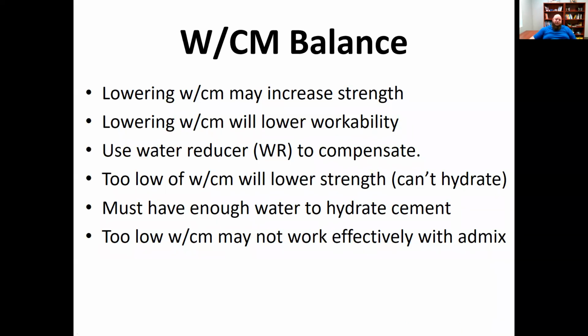The water cement ratio balance is all about lowering the water cement ratio to increase the strength, but lowering the water cement ratio will also lower your workability. So there's kind of a teeter-totter effect where you may get better strengths, but you may have lower workability, so you might want to use a water reducer to compensate. Too low of a water cement ratio, sometimes you may have issues hydrating, or you may be depending too much on your superplasticizer to get your workability, and you may even have some type of chemical shrinkage issue. So you've got to be kind of careful.